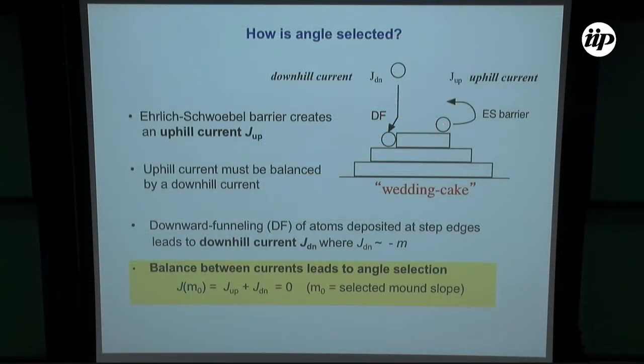The introduction of the Schwoebel barrier says that there is a higher probability for atoms to be reflected from the step edge and go this way than go down. So what will happen to this atom is that once this atom goes back, another atom is deposited, they will stick and give rise to a current of atoms that go up the hill. What are the downhill currents? Downhill currents come from atoms being deposited at the step edge. So if you have a very high, very steep surface, there's a high downward current because atoms are deposited all the time at the step edges and they go down. If the surface is flatter, the atoms are reflected back and you have a higher upward current. It is the balance of these currents that selects the mound angle.